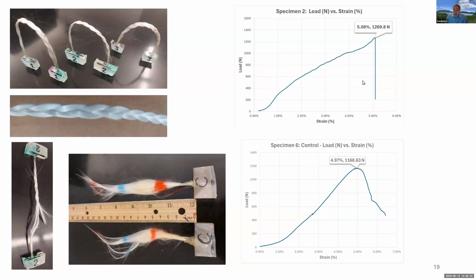This figure shows the test result. For the braided fibers, the maximum tensile force is 1,269 newtons, and the fracture strength is 5%. For straight fibers, the fracture strength is 4.97%, and the maximum load is 1,168. So what does it mean? Based on just this one sample, of course, we cannot make a solid conclusion because we need more samples to test. However, you can see that the braided fibers show a little bit higher deformability, but also a little bit higher load carrying capacity.